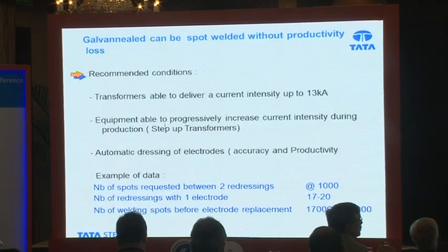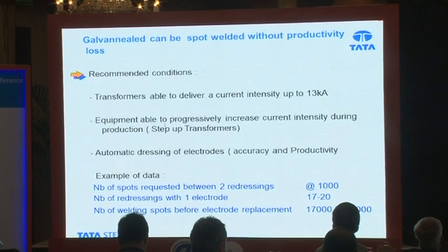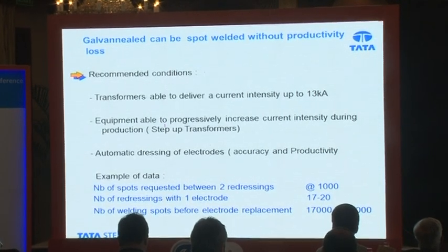Another important thing which I spoke about between GI and GA is the spot weldability. Now, in case of both GI and GA, you need to have transformers which will be able to deliver the current intensity up to 13 kiloamps. The bare steel, which is the one used in India, can be easily welded at even 8 kiloamps. So if the automaker wants to shift, then he has to use higher capacity transformers, and it has to have a facility to step it up.